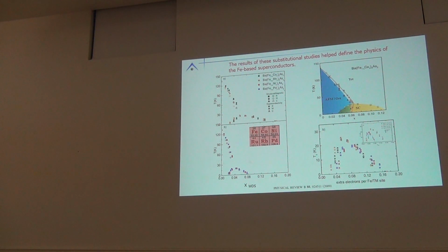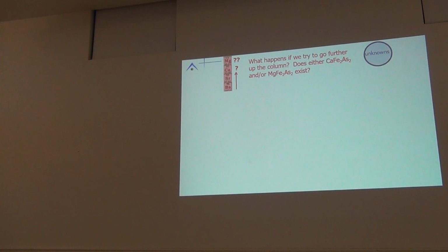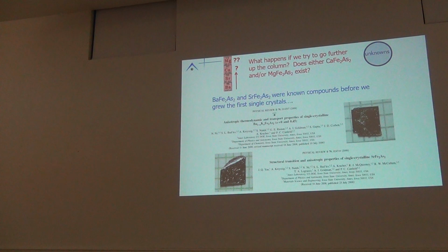Now, that was wanting to look at a specific ground state. You can also explore for unknowns. This is an example of what I would call a known unknown. We have barium, we have strontium. What about calcium? What about magnesium? Barium and strontium were known compositions. Calcium and magnesium were not reported. We were able to grow the single crystals of barium. We were able to grow single crystals of strontium. It's sort of what I would call a clever monkey experiment. A clever monkey can figure this out.